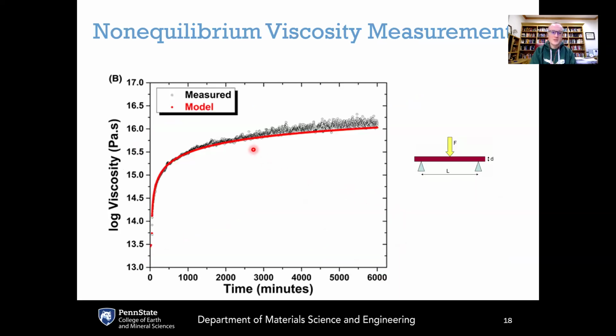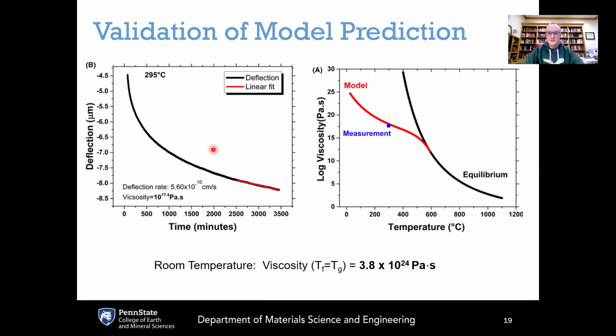This shows an example of the log viscosity versus time. The noisy points here are the experimental data. They're noisy because this involves taking a numerical derivative, and then the model fit using the MAP equation is shown by the red line. The key thing is that the model parameters are the same at all temperatures and all thermal histories, because the model parameters are a property of the glass itself.